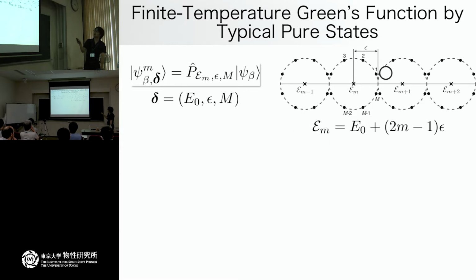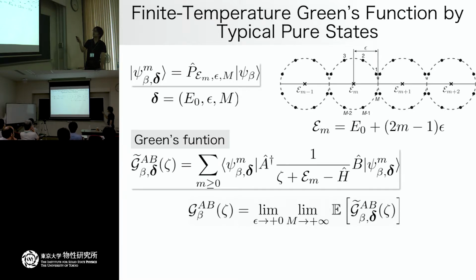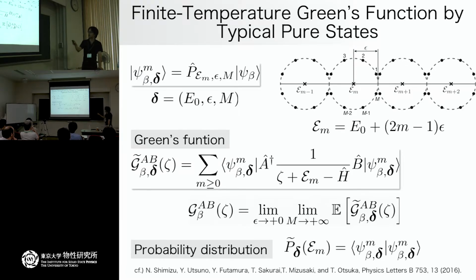Then if you cover your energy axis by introducing this contour integral like this, you can end up with the Green's function by using this kind of spectral projection. And if you take the large discrete point limit together with the small radius limit, where epsilon is the radius of this circle and m is the number of discrete points on this contour, then you can obtain the exact Green's function. And as a byproduct, if you just take an inner product of this projected wave function, then you can obtain the probability distribution as a function of the discretized energy.